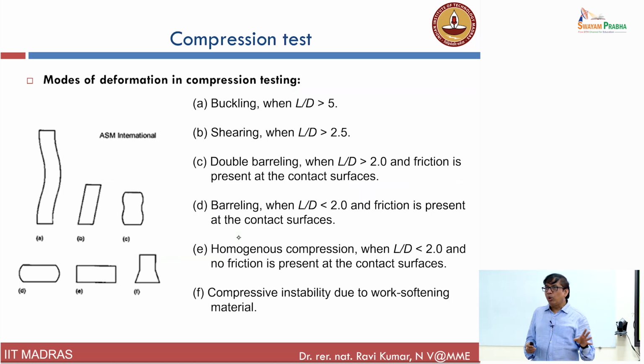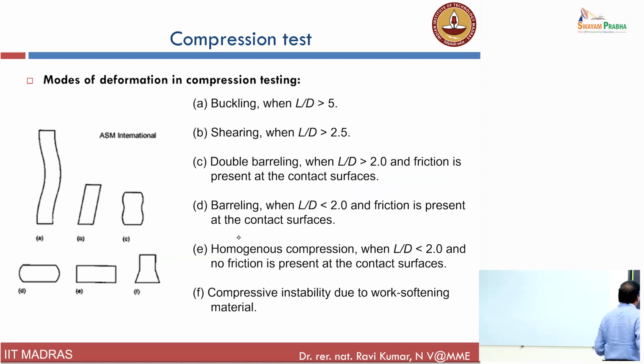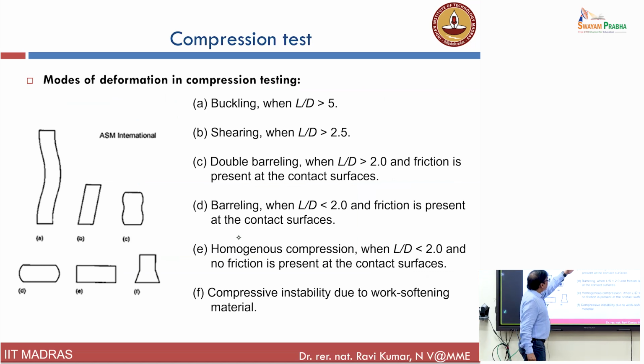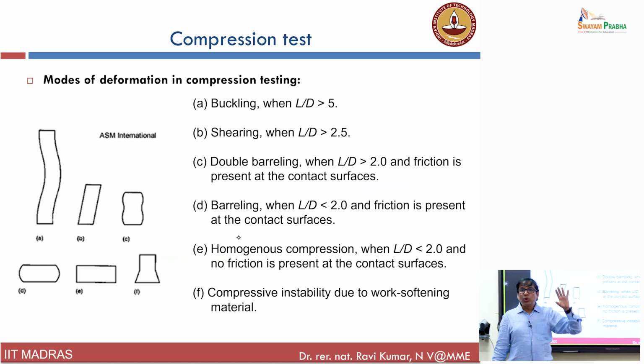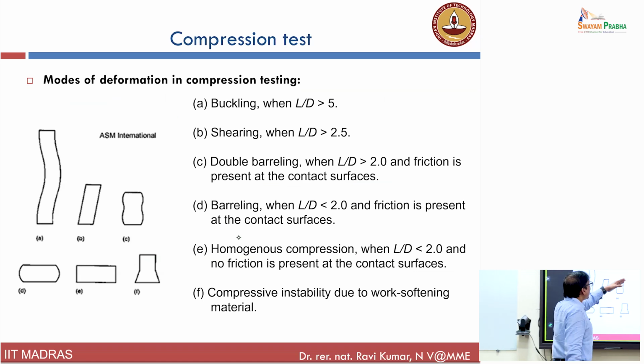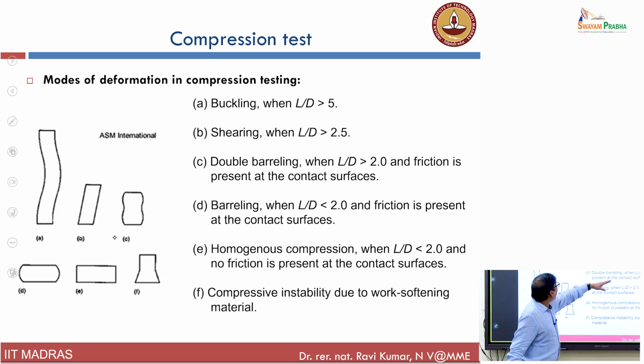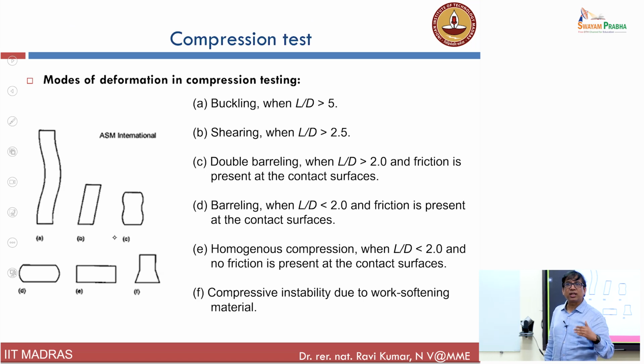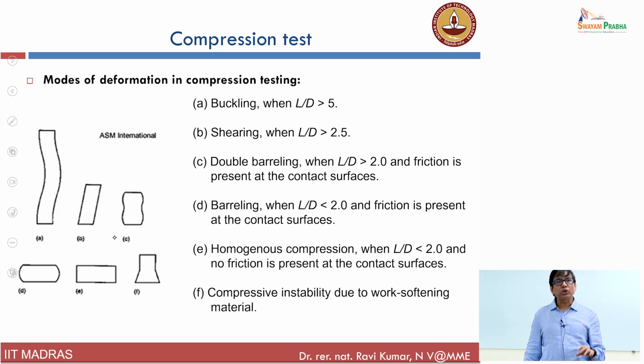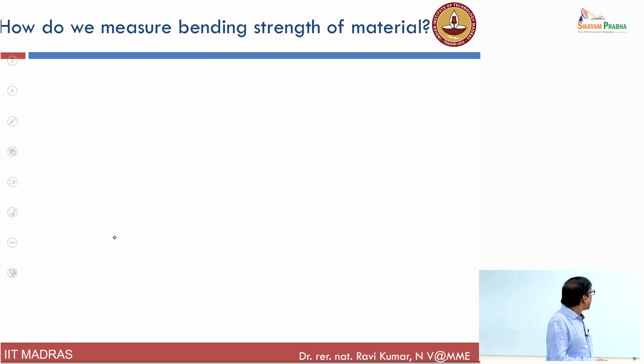The only thing that you must know in compression testing is that you must have the compression coupons in such a way that they don't buckle and don't fail in a mode that they should not. For example, we would like the compression samples to usually shear. So this is the kind of L by D ratio you would like to have. So you typically have compression tests done based on the L by D ratio so that it doesn't buckle, and you have to ensure that it fails by shear and not by anything else. So this is something that you must know.